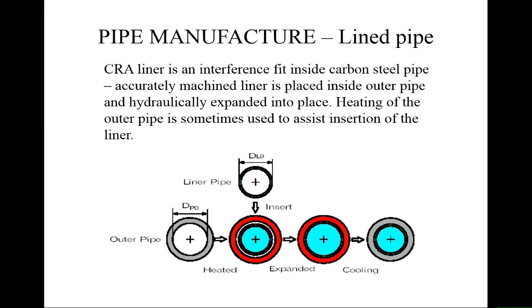Now often the way this is done is to heat the carbon steel pipe up so that it expands, to insert a cold liner pipe, and then allow the cooling to take place so that it contracts and bonds onto the surface. But there's no metallurgical bond in these cases, it's just usually a simple mechanical bond. You can then, during the hydro test, pressurize the inside, and you can expand and plastically deform both, and you may get a metallurgical bond after that point, but it isn't essential. So if the inner liner is breached, you may get some interfacial penetration of your gas or your liquid that's in the pipe, and that can lead to corrosion problems and other things.